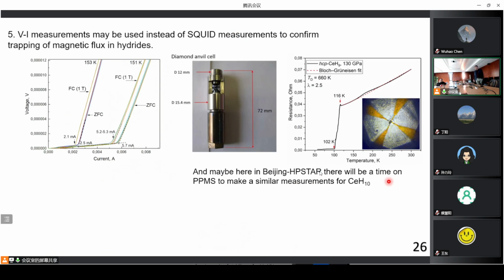You can do it in the same cell where you measured standard resistive transitions, where you studied their dependence on magnetic field. And the next step may be measurements of these loops of critical current in different conditions to confirm that there is trapped magnetic flux, to confirm that there is a Meissner effect in polyhydrides. And I hope that at Beijing HPSTAR, I can also study my cerium sample in the same manner to confirm the first measurements done for neodymium-doped lanthanum H10.